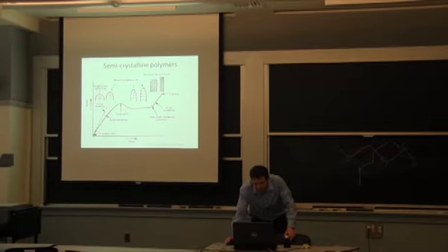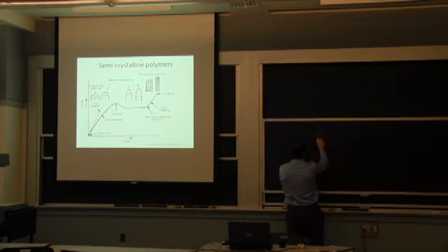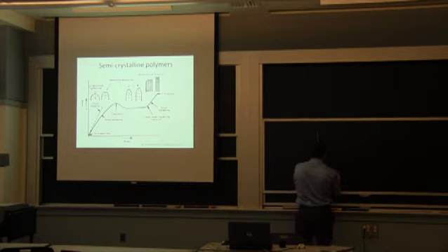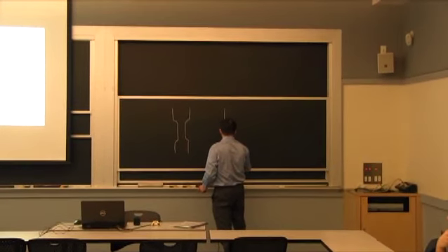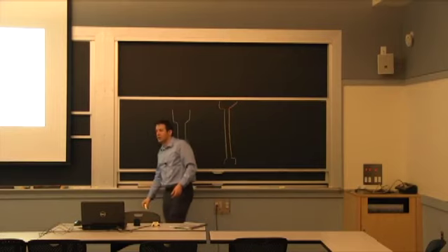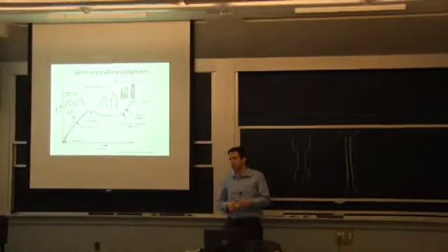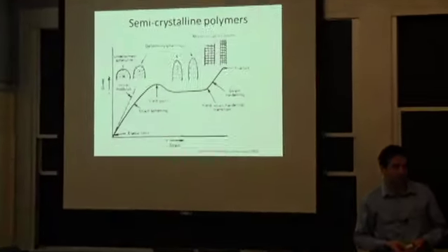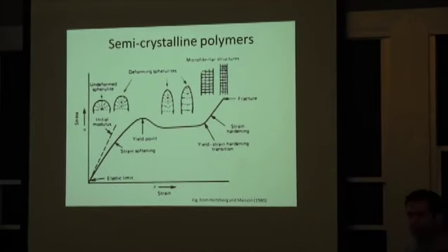The reason why, when we take a piece of plastic in the lab, say we start with a dog bone like this, we can end up with something that essentially looks like this. So we're talking about 300% elongation. You break down that spherulite when you start the deformation, and it becomes more of a fibrillar structure. And that's what nylon cords are made out of. You start producing the nylon as a melt, a little bit like this part is, and then you stretch it to organize more, to orient more the macromolecules and the crystals.